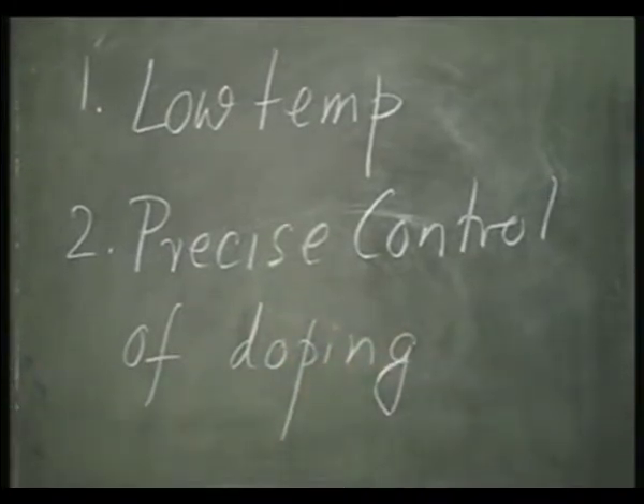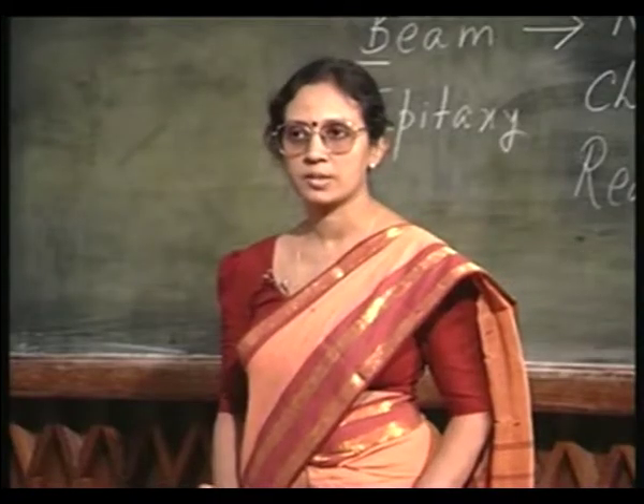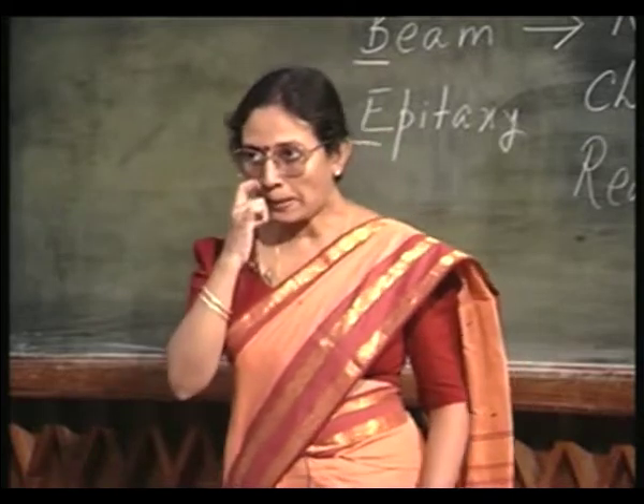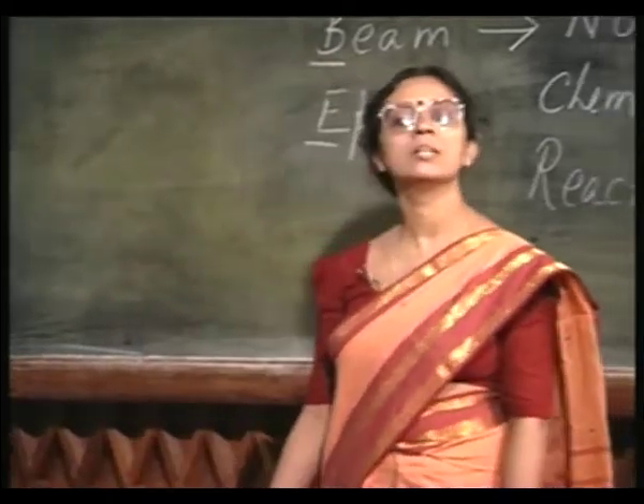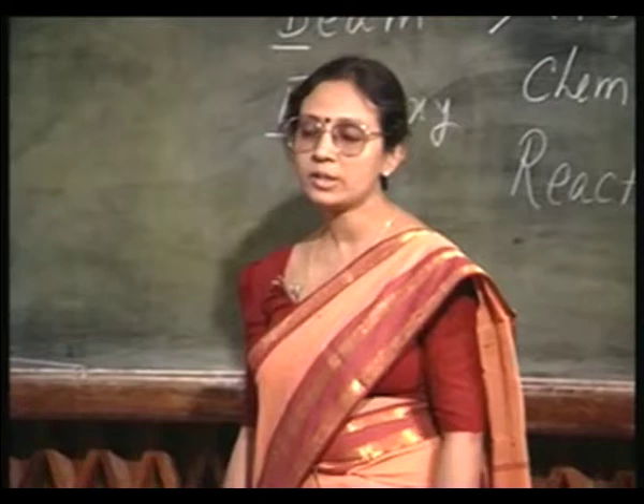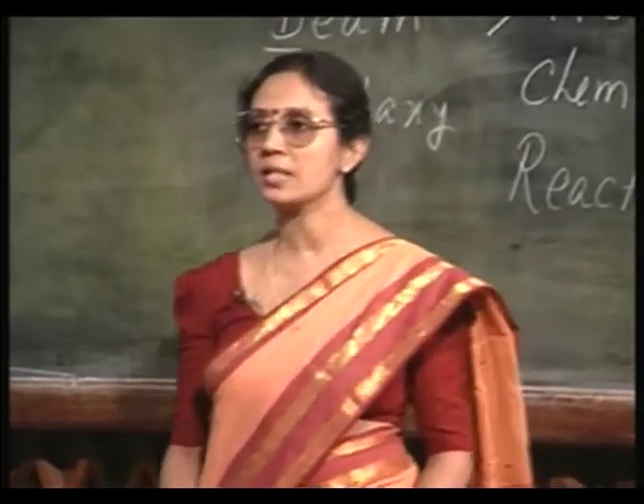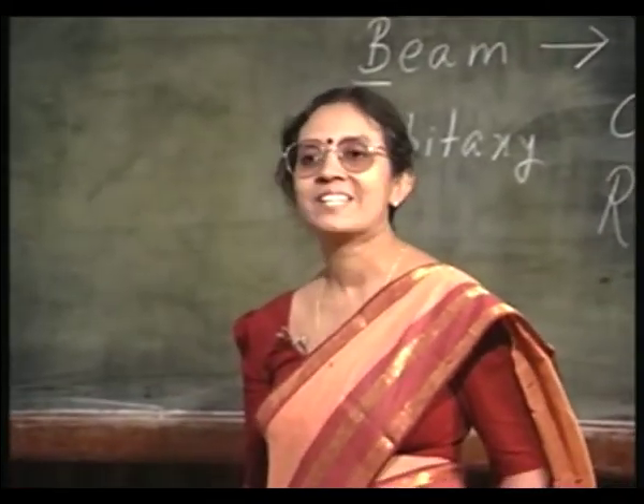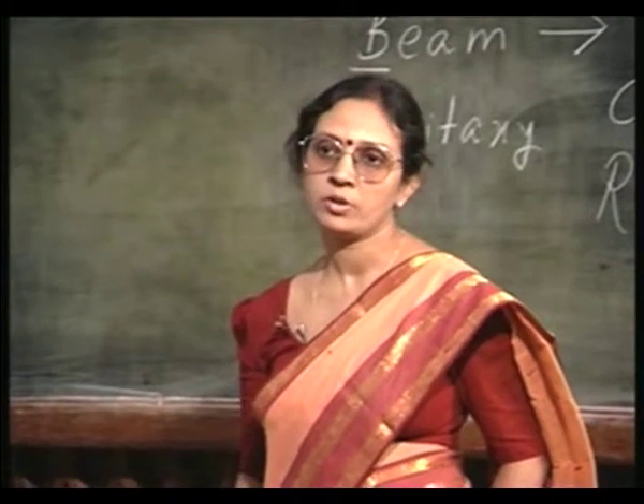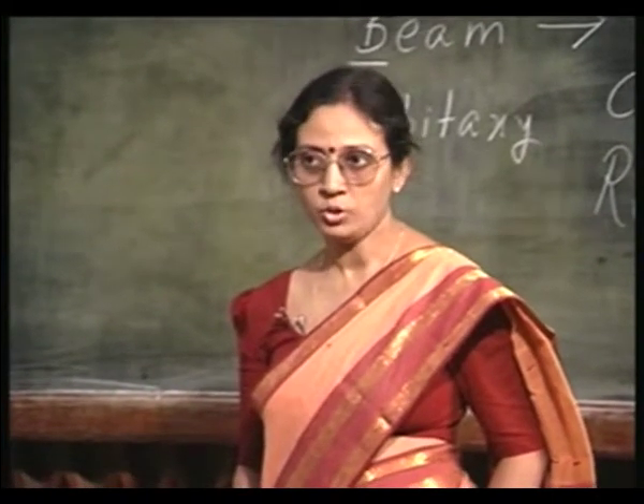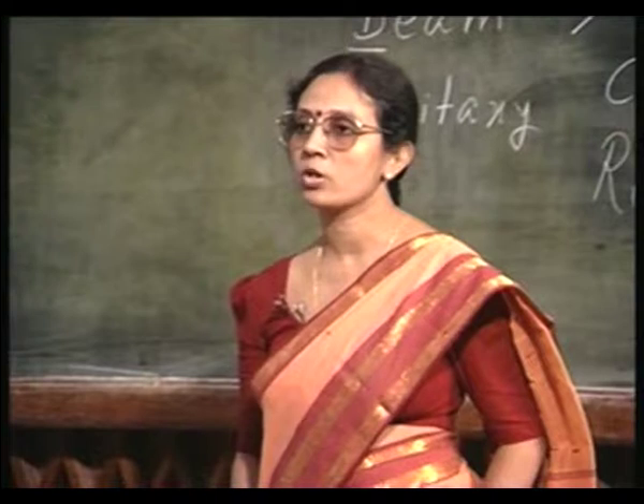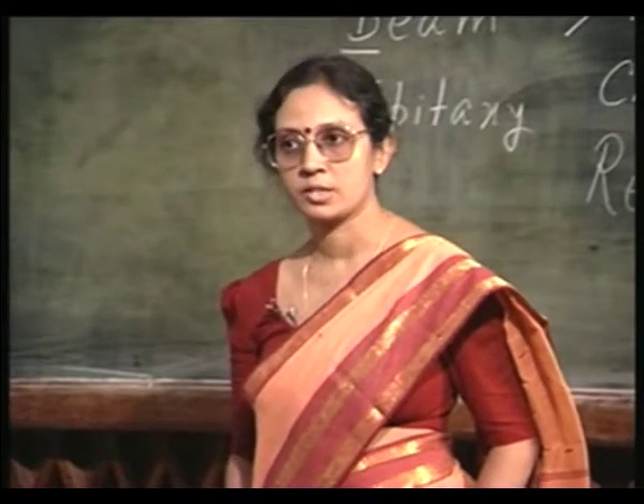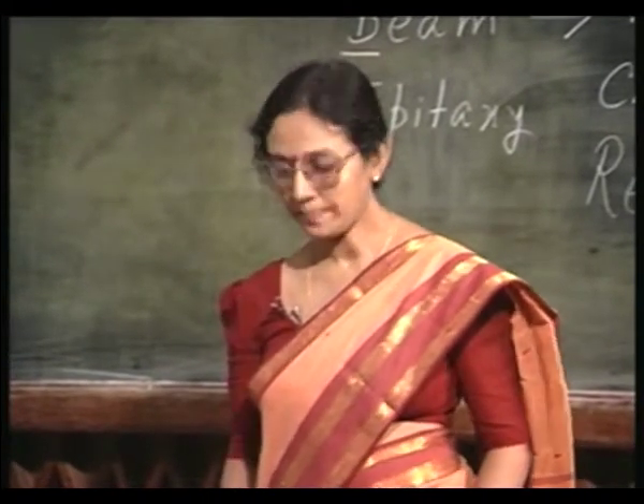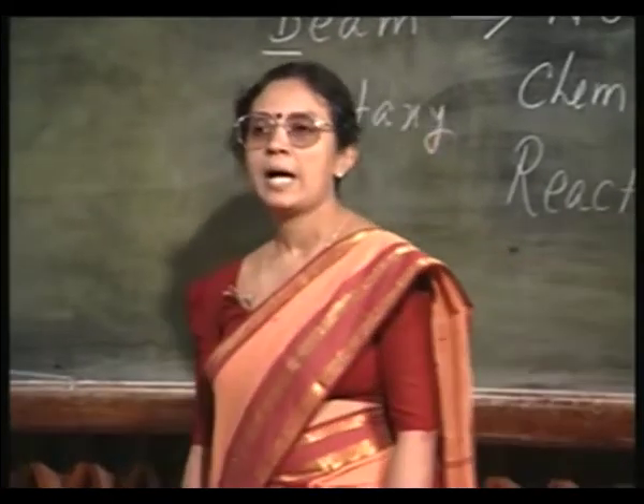Again, this is because there is absolutely no chemical reaction taking place. You are having basically a physical evaporation system. Along with evaporating silicon, you can evaporate measured quantity of dopants. So, the control of dopant incorporation is much more precise.